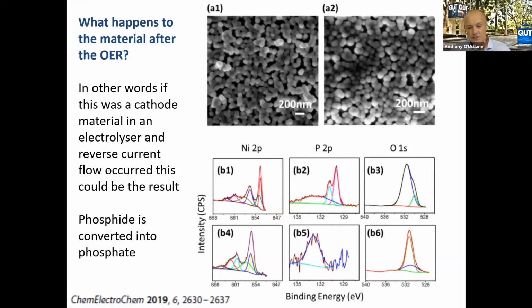That oxidation at the surface really destroys the metal phosphide bond to create metal phosphates at the surface, which are known to be not very active for the hydrogen evolution reaction. So basically, this chemical change that's occurring at the surface of our catalyst is very detrimental to the overall performance. It's something to be aware of if you're integrating materials like this in an electrolyzer that are going to be directly integrated with intermittent renewable energy sources.